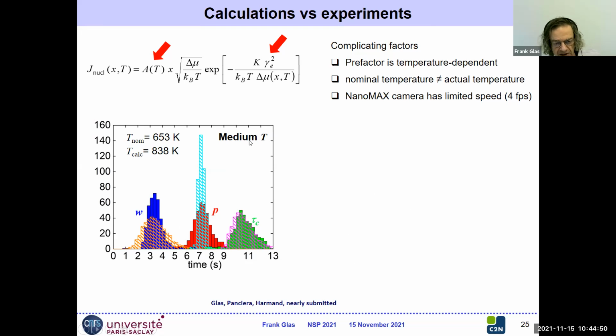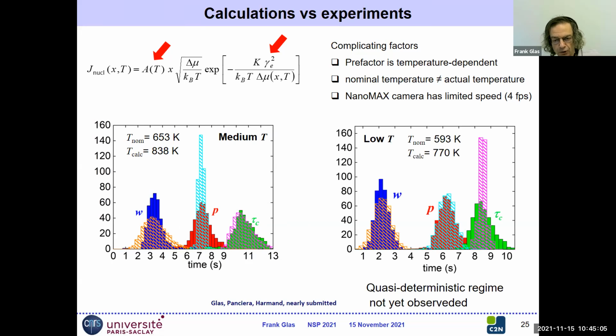So at medium temperature, it's not perfect, but it's not too bad. Well, you would say that maybe the width of the propagation time calculated is a bit too narrow with respect to the one we observed, but there is no great catastrophe. What is annoying is that if we go to low temperature, then, if you remember, in the calculation with infinite time resolution, we expected the distribution of the tau c time, the time between completion of monolayers, to be very narrowly distributed. Now, if I do the calculations to mimic the NanoMAX conditions, especially with a finite frame rate for the camera, this is somewhat broader. So the calculated histogram with the stripes is broader than one single channel. However, it is still somewhat narrower than the experimental histogram.